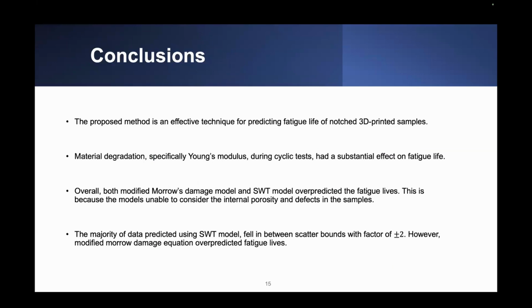To conclude, the proposed method is an effective technique for predicting fatigue life of notched 3D printed samples. Material degradation, specifically Young's modulus during cyclic tests, had a substantial effect on fatigue life. And overall, both modified Morrow's damage model and the Smith-Watson-Topper model over-predicted the fatigue lives. This is because the models are unable to consider the internal porosity and defects in the samples. And finally, the majority of data predicted using a Smith-Watson-Topper model fell in between scatter bands with factor of plus and minus 2. However, modified Morrow's damage equation over-predicted fatigue lives. Thank you.